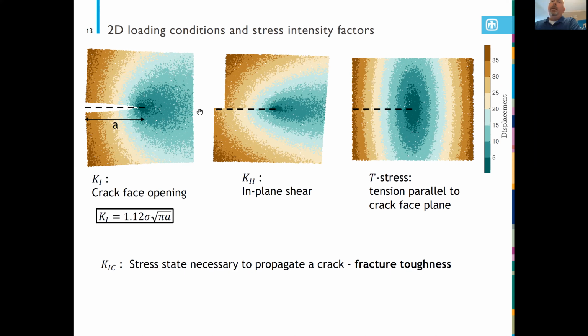So when we're going to be applying our displacement modeling to this atomistic representation, we will actually have a combination of these and higher order terms. We can go to as high order terms as necessary. But once again, I'm trying to find K1C, that's the fracture toughness, the critical stress state necessary to propagate a crack. I want to note that these Williams expansions that I talked about previously are actually, if you were to take your favorite fracture mechanics book and look up, the standard approach would be to look up a given geometry and a given loading condition,